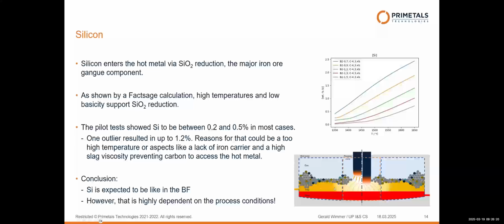And second point is we have here a big interface between metal and slag. So this furnace is very big. We have very long residence time. So the material has quite a long time to get in equilibrium. That's why we have plotted here typical equilibrium values calculated with FactSage. So we asked if we have a metal rich in carbon and a slag rich in SiO2, what would be the equilibrium value of silicon in the metal, and calculated this for different basicities.